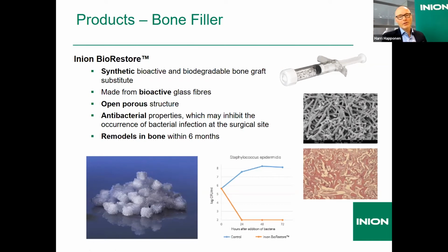The very important feature of the bioactive glass is their antibacterial properties, which is caused by the increased pH during the degradation of the bioactive glass. The pH is increasing to around 10 to 11, which inhibits the bacterial growth. And we have selected the bioactive glass material in Inion BioRestore so that it completely remodels the bone in 6 months. You can tailor and change the degradation time of the bioactive glass as well by changing the raw materials of the glass. So as a window glass, it's non-resorbable, but when you change the properties, you can make it also resorbable.